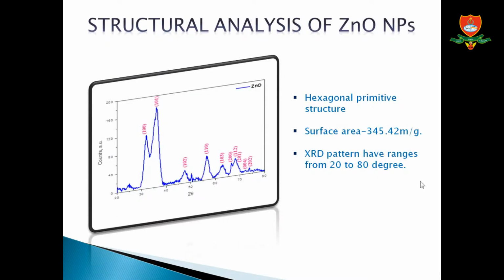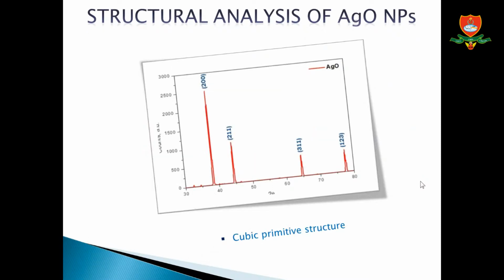Structural analysis of zinc oxide nanoparticles. The XRD technique uses the scattered intensity of an X-ray beam on the sample. Zinc oxide nanoparticles were recorded in a range of 20 degrees to 80 degrees. All the different peaks are attributed to a hexagonal primitive structure.